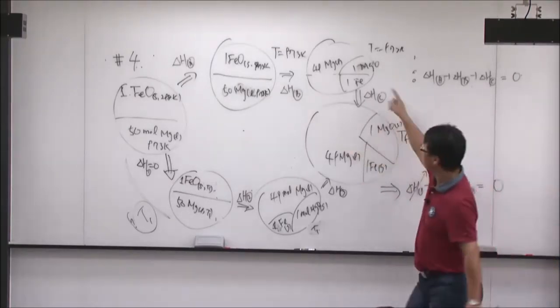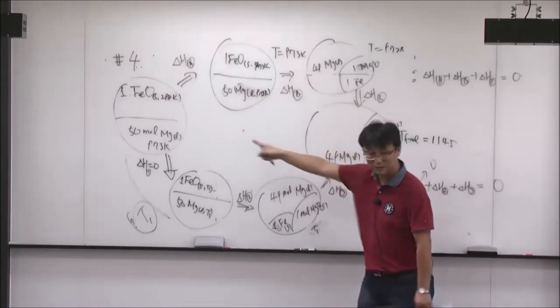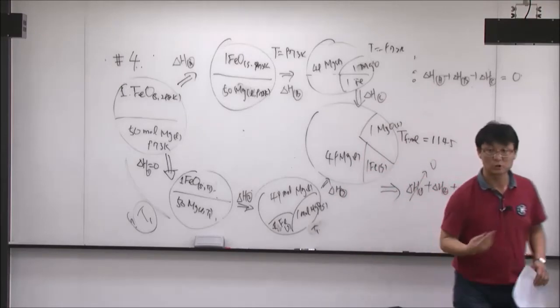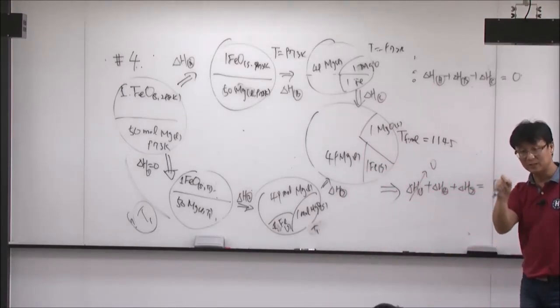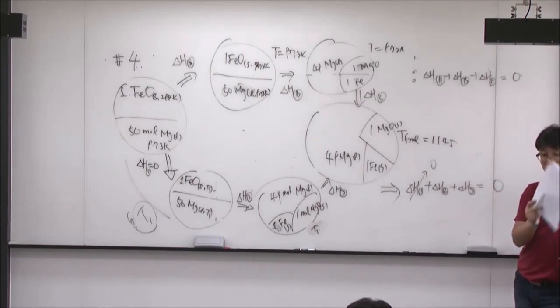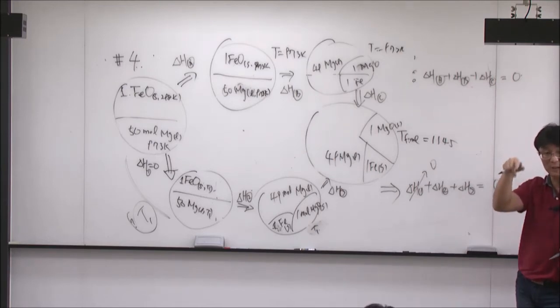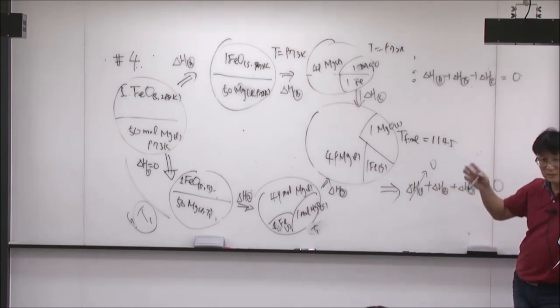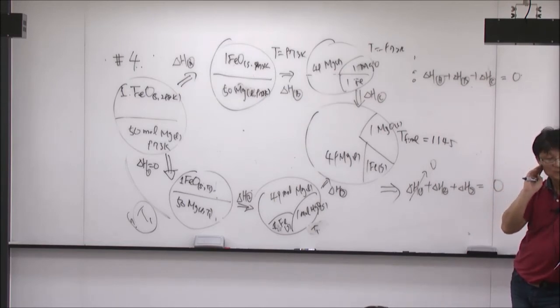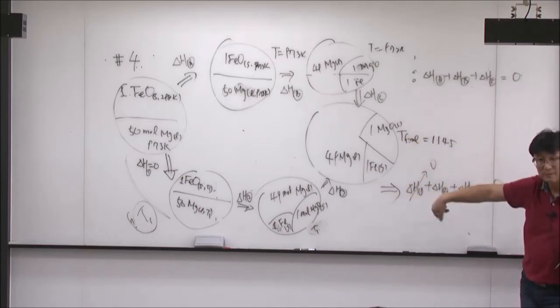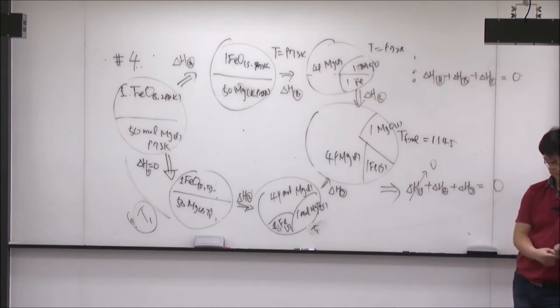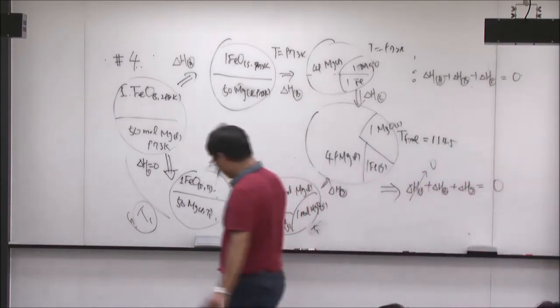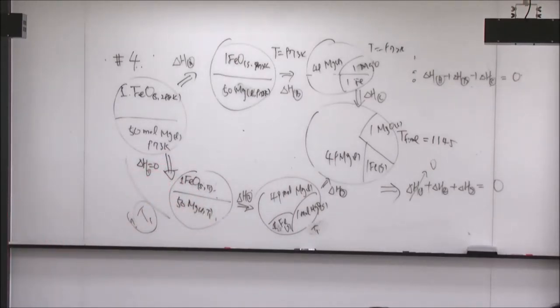Last question — the Ellingham diagram. I'll tell you what mistakes you are typically making. There are almost no students who got the full mark here — only one or two probably. There are two typical mistakes. First: when drawing a line from the origin point on the Ellingham diagram to read off the log PO2, H2/H2O ratio, or CO/CO2 ratio at a given temperature, more than 20% of you drew the line starting from the wrong point. The line must start from the correct origin point — that's where the mistake is.